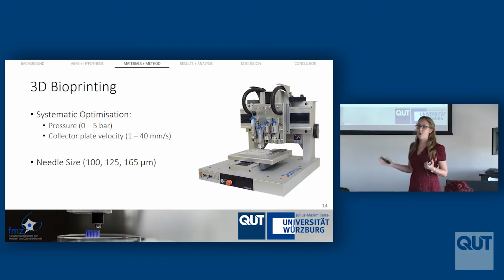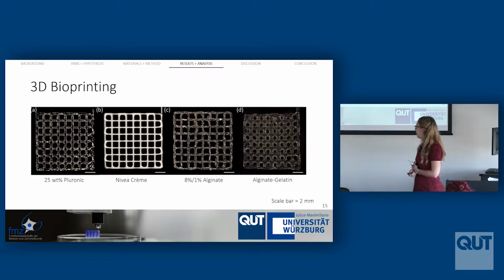So here are my optimized structures that I was able to make with those different concentrations. I decided that 25% weight Pluronic gave me these beautiful structures. Here's Nivea cream, just looking stunning as always. My 8% alginate with the 1% cross-linking solution gave me a reasonably nice looking lattice, and then our alginate gelatin was our really biocompatible one, which was great. So these are all directly bioprinted.